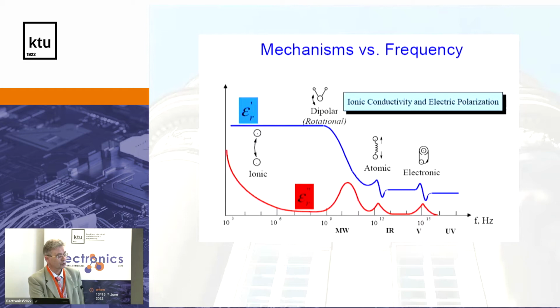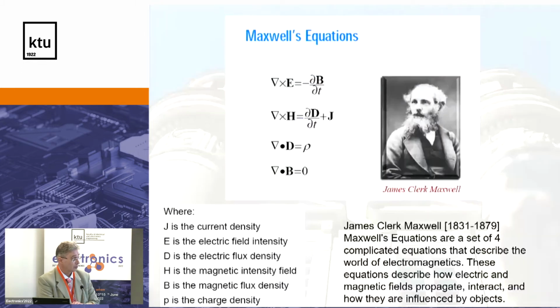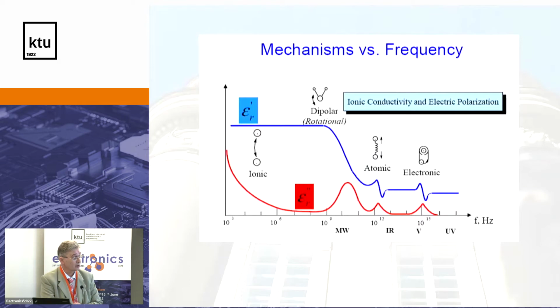And of course, when the real part decreases, due to the Kramers-Kronig relation we have a change in the imaginary part of permittivity. So the red curve is the dielectric losses, or imaginary part of permittivity, and the blue one is the real part of dielectric permittivity. If you go further to infrared or high frequency microwaves, you have atomic vibrations, polar vibrations, because in the crystal lattice you have modes of vibration of atoms, and they are transversal and longitudinal, and transversal polar modes interact with the external electric field, and you have absorption, and this is the so-called resonant dielectric dispersion. And you have such peaks, 1 is shown, for example, but in complicated materials you will have a huge bunch of them, a whole set.